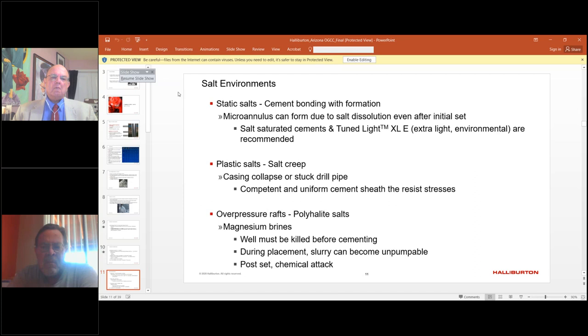The last one that we have here, the last category, are overpressured rafts, polyhalite salts. There's one that we came across that's a magnesium-based brine or magnesium chloride, which is what we'd classify as a tachyhydrite as opposed to a halite. And there's two issues we have here. A magnesium brine will contaminate the cement, and we get a chemistry resulting reaction called brucite. And the brucite basically makes it so thick that it almost becomes immobile, and we mostly won't be able to finish placing the cement. It'll lead to an early termination of the job. Next slide, please.